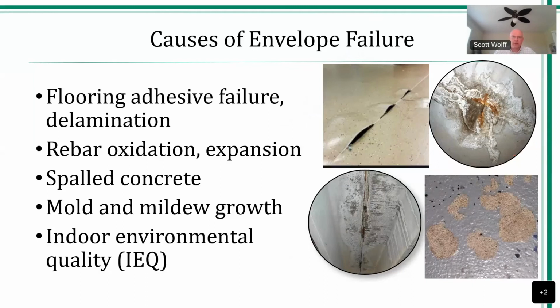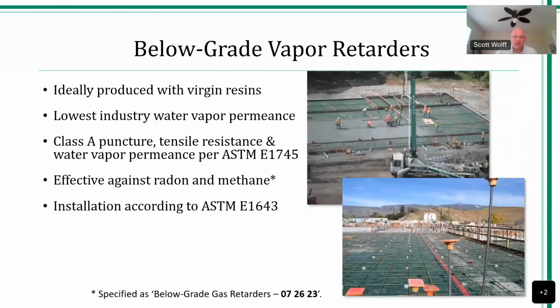So, other causes of envelope failure, obviously once water gets in: adhesive failure of VCT type flooring finishes, and then the aforementioned rebar oxidation. This creates spalling. Epoxy floor finishes can start delaminating where we have high hydrostatic pressure and we didn't have an underslab waterproofing. That water is always going to try to seek the lower vapor pressure. So higher pressure seeks lower pressure. So just some of the aspects here.